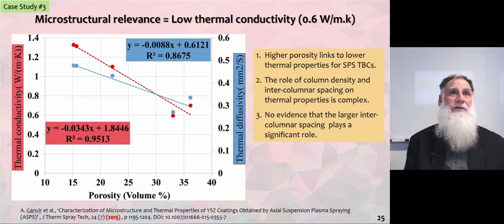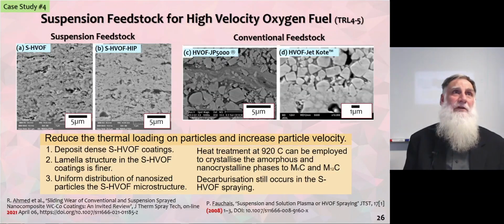So there is a lot of evidence as well from this work that the thermal conductivity also was very low, where a low thermal conductivity is much preferred. The higher porosity links to lower thermal properties for the suspension plasma sprayed thermal barrier coatings. The role of column density and intercolumnar spacing on the thermal properties was quite complex, and there was no evidence that large intercolumnar spacing played a significant role. So there is a lot of evidence that these coatings have great functionality.